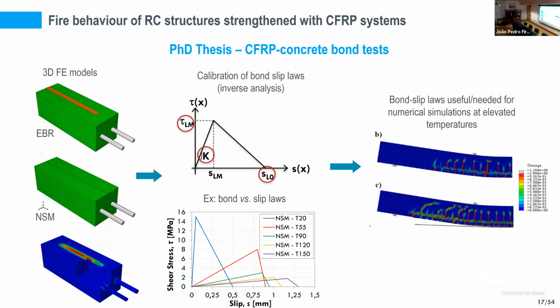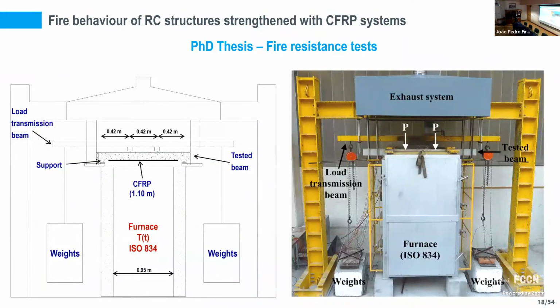With these bond laws that were calibrated, we were able to explicitly simulate the debonding of the CFRP system during fire. And this is a significant advance in the literature at that time. But those numerical models needed to be calibrated with experimental data. So we also did some fire resistance tests to compare with numerical results.